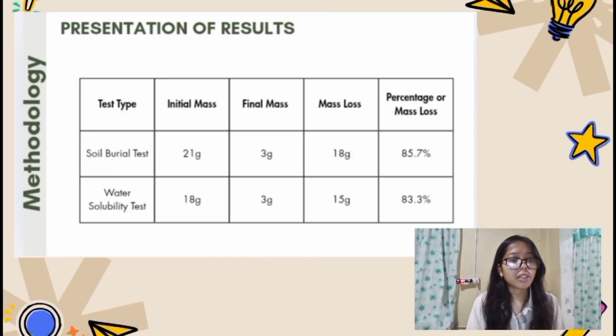And now for the presentation of results. The table presents a quantitative analysis of the bioplastic physical degradation across 2 distinct environments, starting with the soil burial test. The material began with an initial mass of 21 grams and was reduced to 3 grams after the testing period. This resulted in a total mass loss of 18 grams, representing an 85.7% decomposition rate in soil.